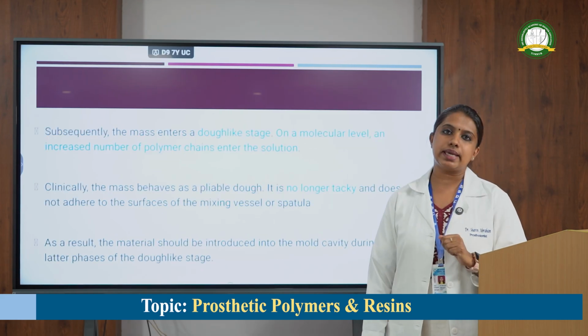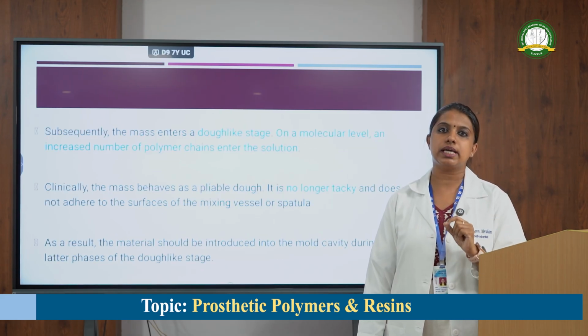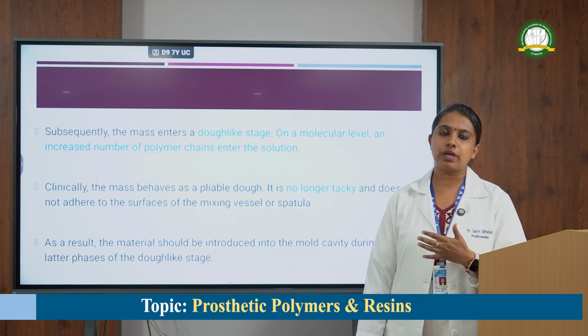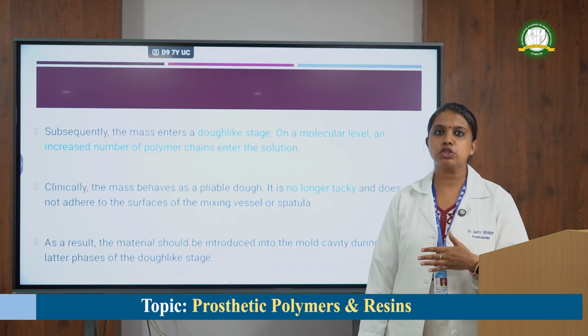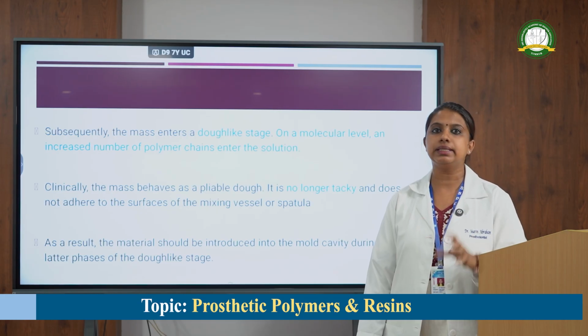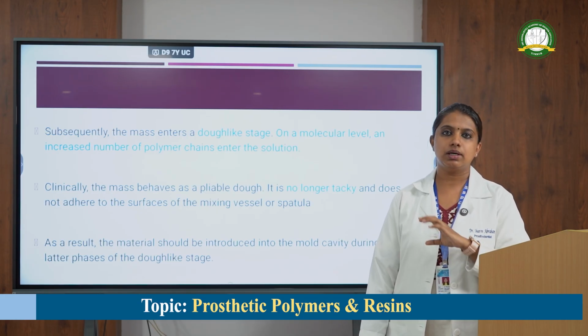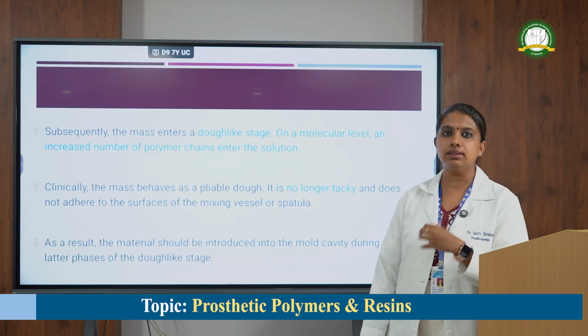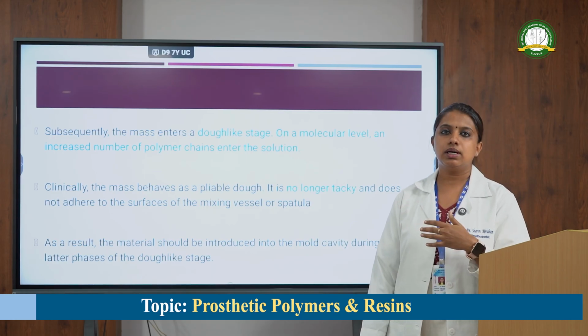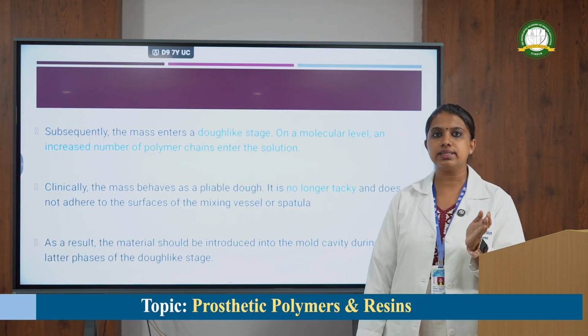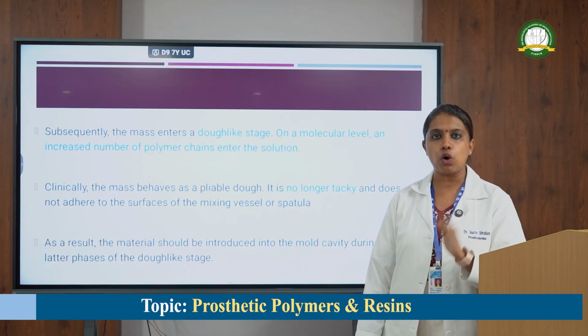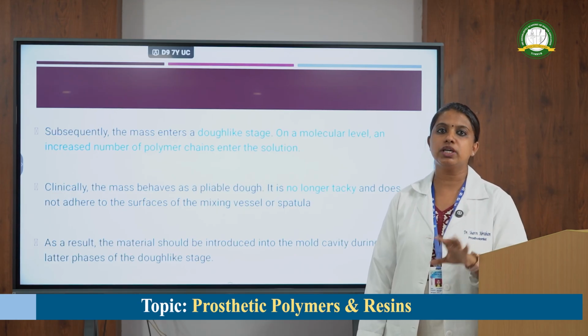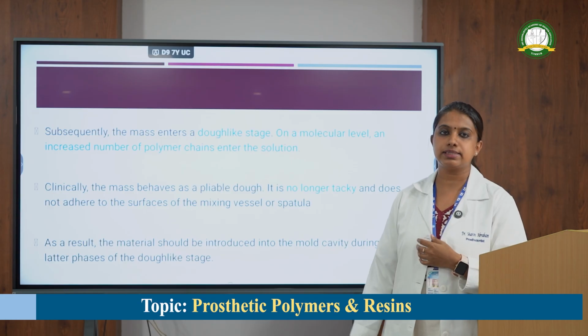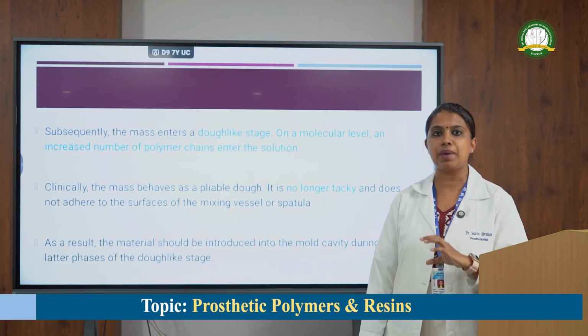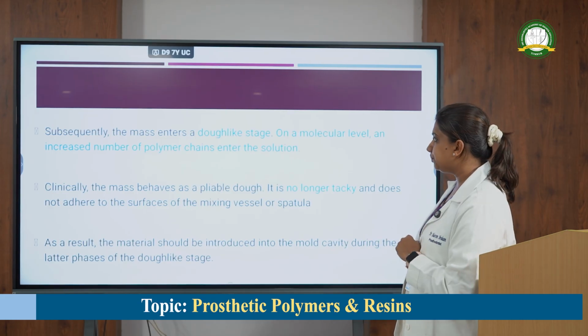Then comes the dough-like stage. Now, dough-like stage is the most important stage in the fabrication of complete dentures and when you're packing the heat-cured resins. In dough-like stage, the polymer beads is completely wetted by the monomer and the consistency will be like a dough. It's more pliable in nature. Why this stage is ideal is because during this stage, when you pack it in the flask or into the mold, it will adapt to the shape of the mold, unlike any other stage. So, dough-like stage is the ideal stage to pack the resin into the flask.